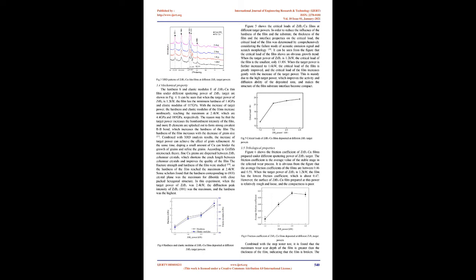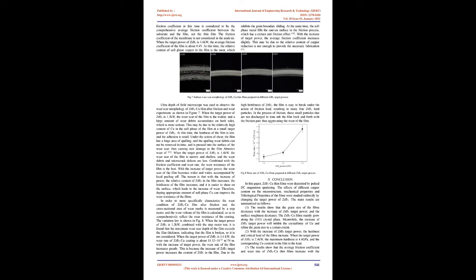3.4 Mechanical property. The hardness H and elastic modulus E of ZrB2-Cu thin film under different sputtering power of ZrB2 target are shown in Fig 4. It can be seen that when the target power of ZrB2 is 1.2 kilowatts, the film has the minimum hardness of 1.4 GPa and elastic modulus of 117 GPa.